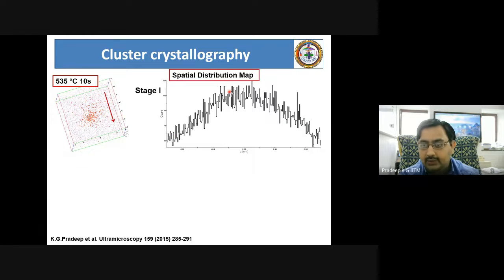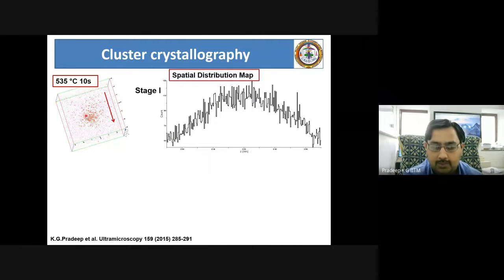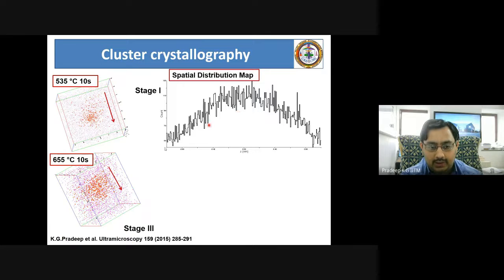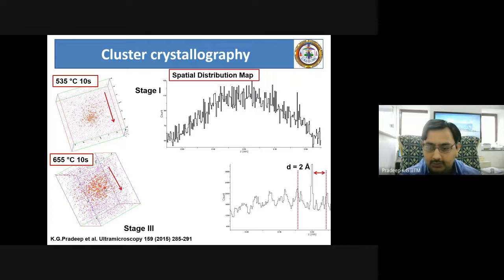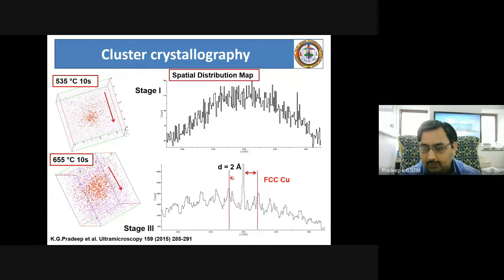And in this case, you see there is no correlation as a function of distance. So you can say the cluster of copper atoms have come together to form this kind of a 3D volume, but there is no crystallographic basis for it. You look at stage 3, a slightly annealed state, take the same single copper cluster, slightly coarsened in size compared to this one. And as you measure the same spatial distribution map, now this time you are able to see a perfect correlation in the intensity of the spatial distribution at neighboring distances, which means the distance between the two maximum intensity peaks is 2 angstrom.